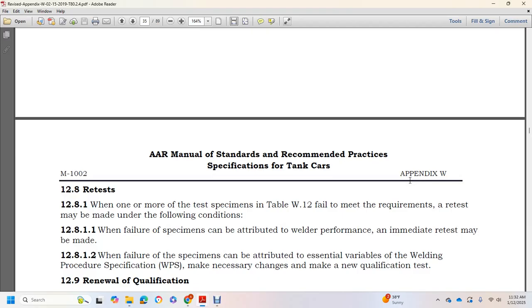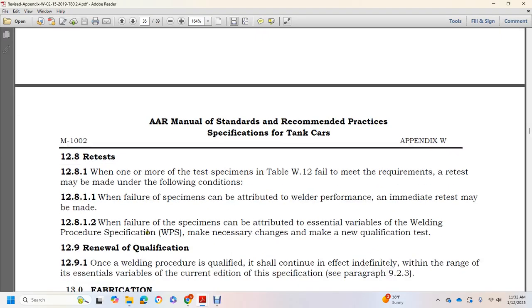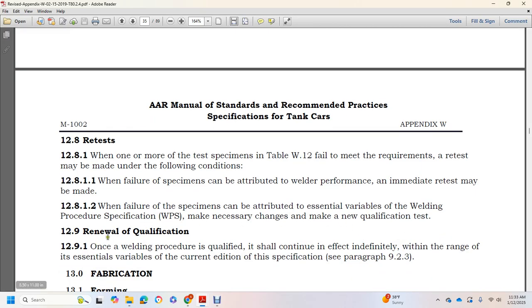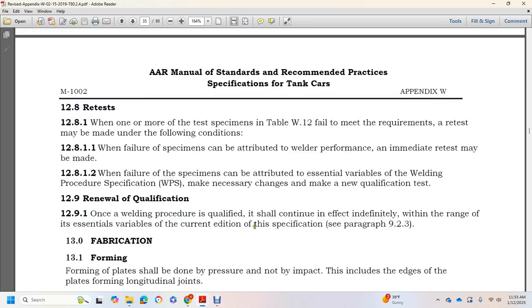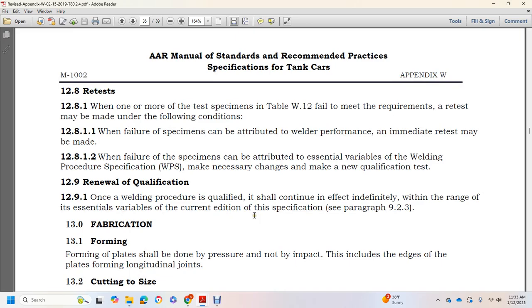12.8 Retest. When one or more of the test specimens of table W12 fail to meet the requirements, a retest may be made under the following conditions. When the failure of the specimen is attributed to welder performance, an immediate retest may be made. When the failure of the specimen is attributed to an essential variable of the welding procedure specification, make the necessary change and make a new qualification test. 12.9 Renewal of qualification. Once the welding procedure is qualified, it should continue indefinitely without change of the essential variables of the current edition of the specification. Chapter 13, Fabrication.